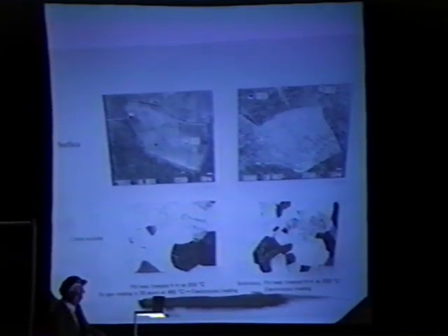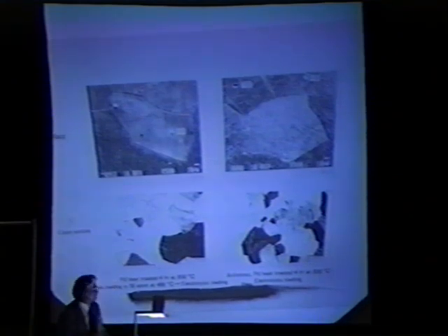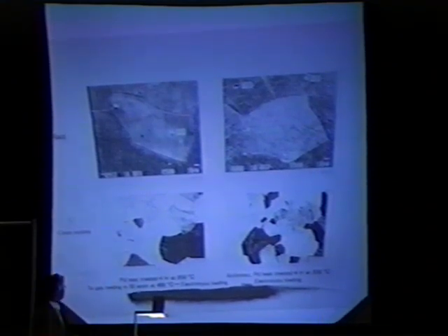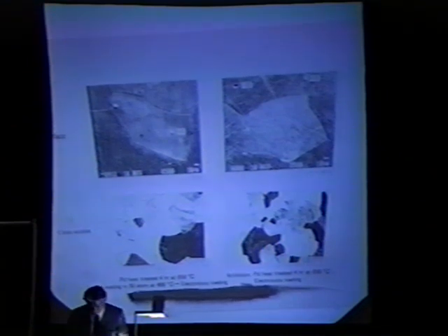This is a microstructure after electrolysis loading. This is the ordinary electrolysis procedure. We can see many slip bands inside the grain. However, we cannot see much deformation defect for the high pressure and high temperature loading.